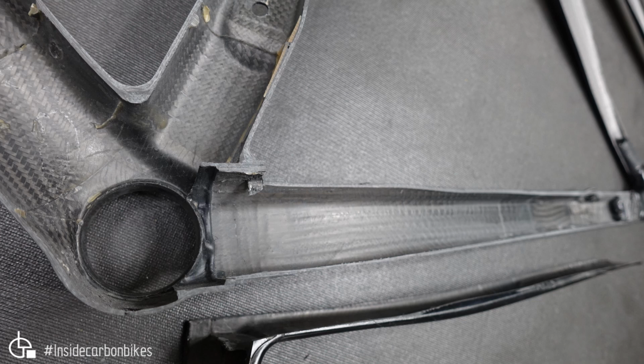Now, because the front triangle is made on a mandrel, you can control the internal dimensions of that bond interface very accurately, and also you can control the outer shape of the chainstay very accurately. So you've got good control of that bond line thickness. Now that's a real key for good structural bonding, to have uniform adhesive thickness. So that can be maintained well, and you can see clearly in this case, they don't have to allow for variations in those mating surfaces, which then gets filled with adhesive, or in most cases, they don't put enough adhesive in and you get voids in those areas. So they've got really good control over the adhesive.